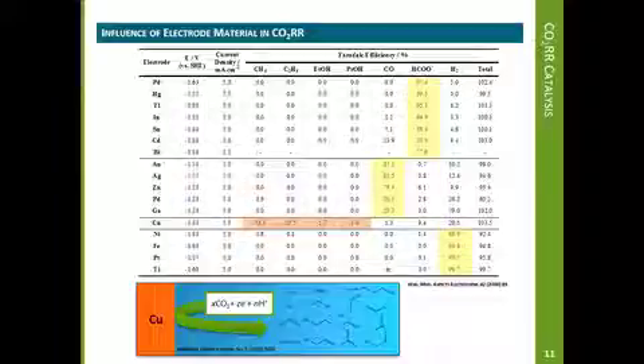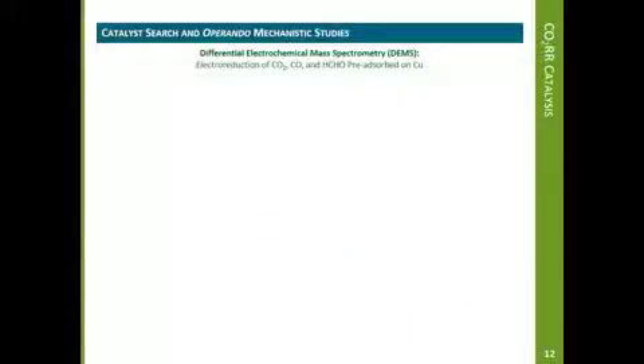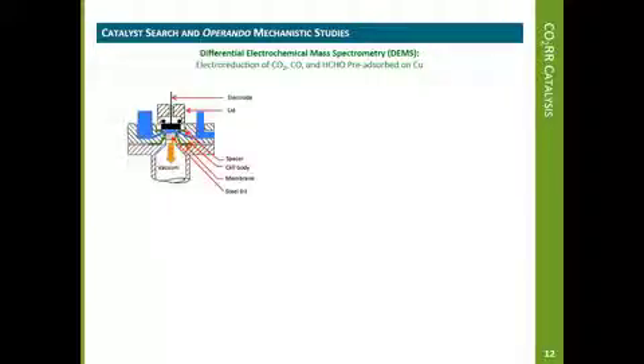The fact that 16 reduction products have been detected so far in both the liquid and gaseous phases suggests the complexity of CO2RR in copper. To understand the reaction mechanism of CO2RR, copper electrodes were exposed separately to carbon dioxide, carbon monoxide, and formaldehyde prior to the electrochemical reduction in a solution that only contains 0.1 molar potassium bicarbonate.